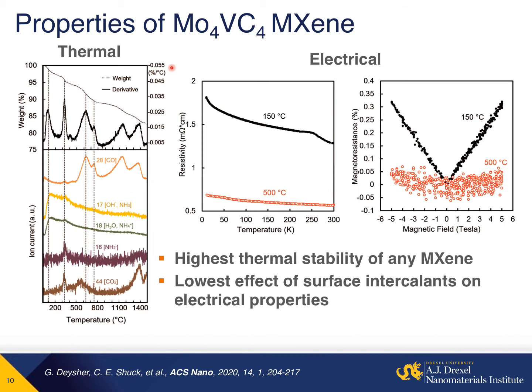Once we saw that this occurred, we produced two separate samples. One film that we annealed at 150 degrees to release all of the water, and one film produced after annealing at 500 degrees to degrade and release all of the intercalant. Typically, what you will see here is a large decrease in the electrical conductivity when you have an organic intercalant remaining on the surface, as it changes its electron density. What we saw here is that the conductivity went from about 250 Siemens per centimeter up to about 830 after this process. However, most MXenes will experience a 1 or even 2 order of magnitude change in conductivity after this. What this means is this MXene, due to its thickness, has a higher protection against the organic intercalant changing its electron density.